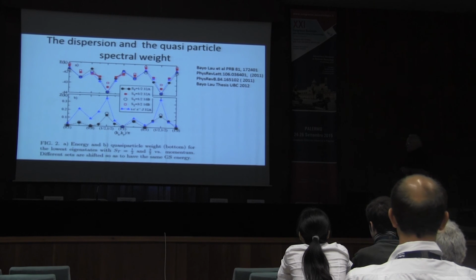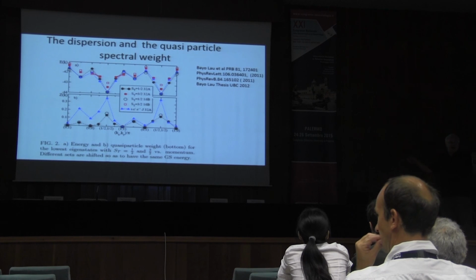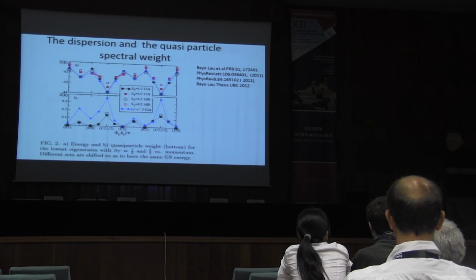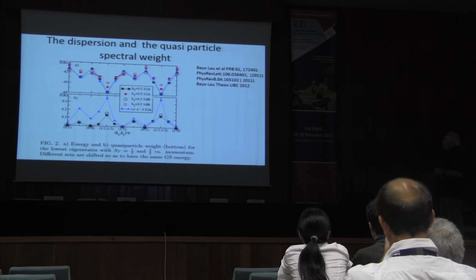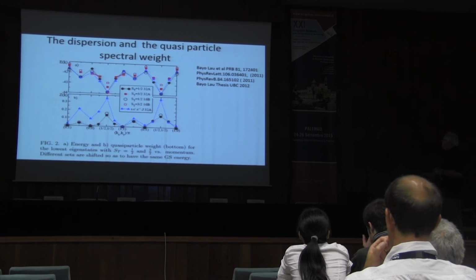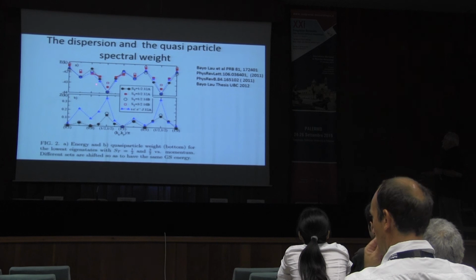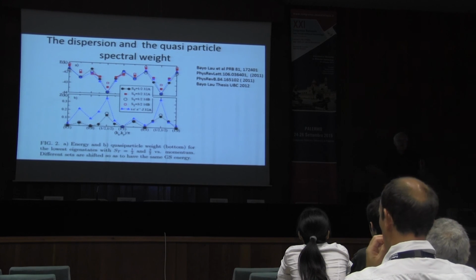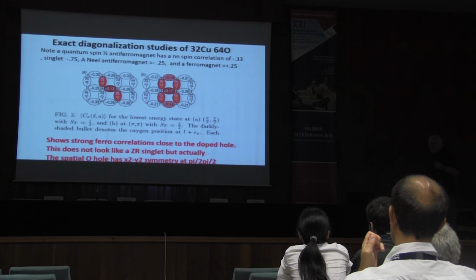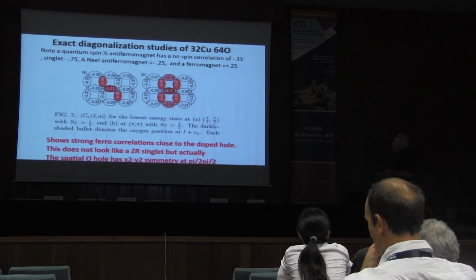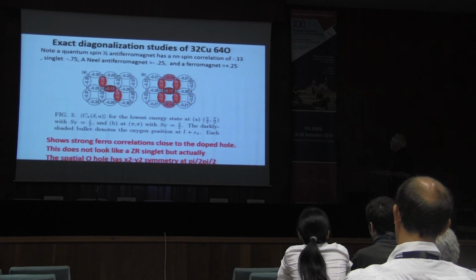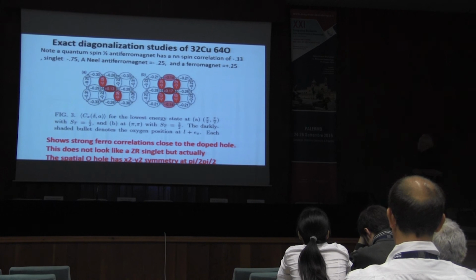When you do that, and you do this exact calculation with 32 copper sites, which is horrendous, I think the basis set was 10 to the 18th or something like that, which he could reduce down by using certain symmetries and so on. Anyway, you get pretty well the same dispersion as you got with the t-J model. Well, that's very interesting. But the physics of this is completely different. If you now look at the correlation function, what is the spin correlation between the copper spins here at these vertices around an oxygen hole, where the oxygen hole, however, has the full periodic symmetry. It's at pi over 2 in momentum space. But you can calculate that correlation function because he has all the eigenfunctions.